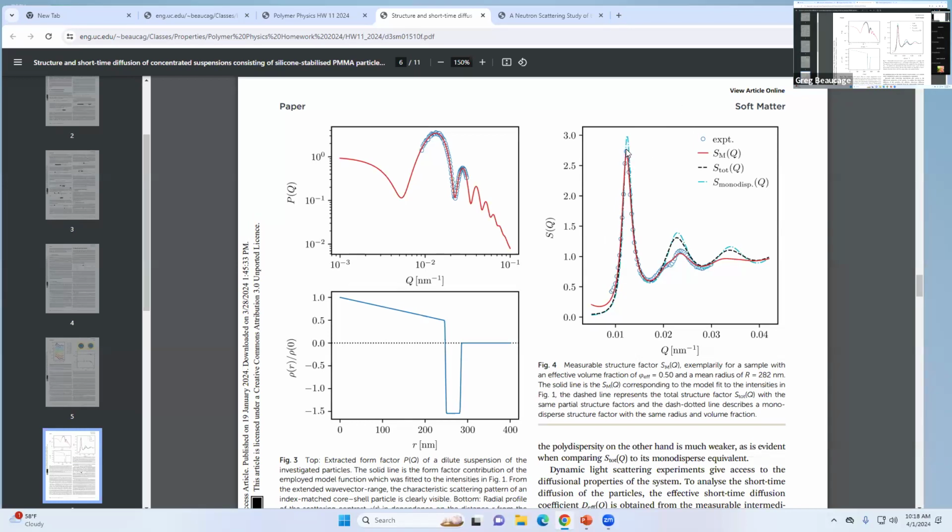And then this repeats. In other words, if they're piled up at the surface, then you have another, larger excluded volume that excludes to the next shell. So that's this one. Then the ones that were excluded from that pile up on the outside of that. That's the second order interaction. Then that repeats ad infinitum until you get to one, where the structure factor is one, you have no ordering at long distances.